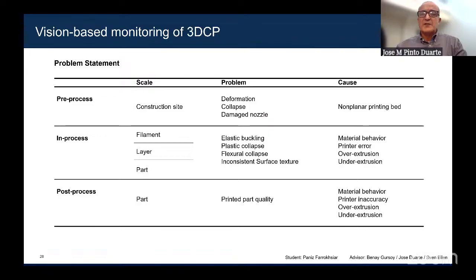There are different ways of using systems like these. One is before you start printing, like for instance, if you want to print on a site that's not leveled or that is not regular. We use this system to create a 3D model of the site. It will scan the site, and it will adjust the toolpath to the irregularities of the terrain to make sure that the nozzle, for instance, does not get buried in the ground. So this is a use of the system before starting printing.